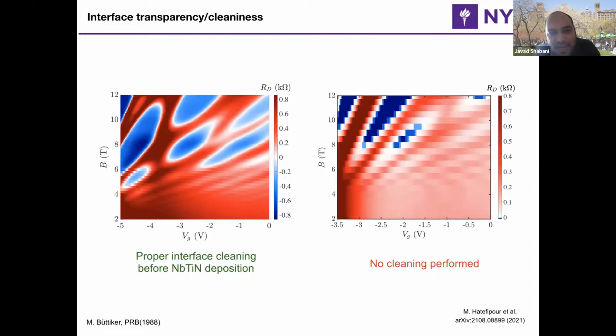So if you look at the right-hand side, you see still some quantum Hall effect with some dark blue region. Maybe the coloring was misleading. If you look at the color bar, you see that the negative resistances now on the right graph are very, very small. On the left, it's minus 0.8 to 0.8 kilo ohm. Now on the right-hand side, when the interface is not cleaned at all, you barely see anything negative.